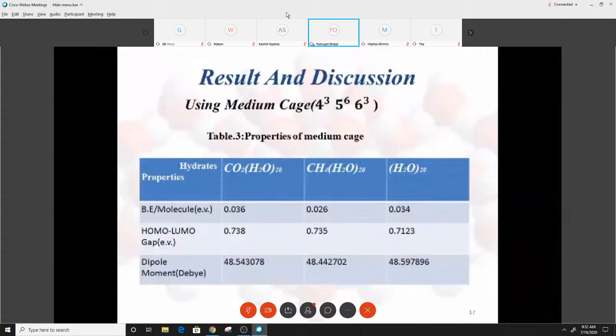But if we compare the small cage structure with medium cage structure, we found that the binding energy per molecule of any hydrate using medium cage is very much smaller than using small cage structure, and the dipole moment using medium cage is much larger than using small cage structure. So the conclusion made by comparing properties between two cases is that the hydrate structure made from medium cage is less stable and more reactive than the hydrate made from small cage structure.